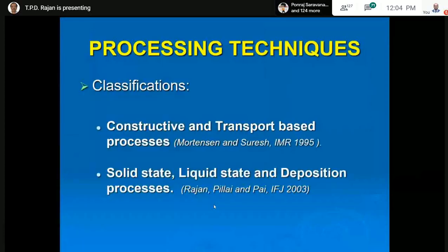So in a conventional thermal barrier system or thermal barrier coating, you can see there is a thermal stress at the surface. So you have a cladding between a substrate and the ceramic tile. Because of this thermal stress, cracking and spallation takes place. But if this integrated advanced thermal barrier coating with the composite integrated structure is there, then the thermal stress is smooth, so that it cannot delaminate. That's why people have started using these functionally graded structures for advanced heat shielding materials.